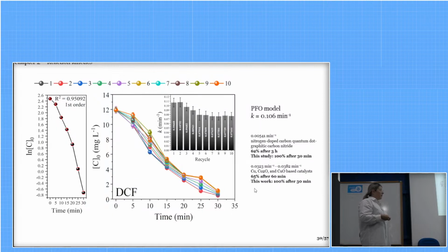For diclofenac, the pseudo first order model also represented the process better. Here we can see a higher decrease after the third recycle, but it remained stable after the fourth and fifth recycle. And in this study, we were able to mineralize 100% of the diclofenac concentration tested after 30 minutes, while the literature reports approximately 62% and 65% after 60 minutes using other catalysts.